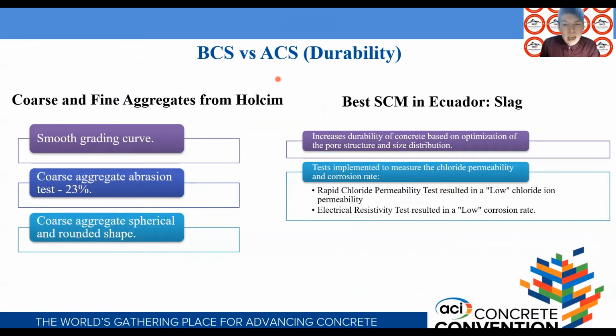In durability and performance, the particle size distribution of the mixture resulted in a smooth grading curve that meets allowed limits based on the characterization of coarse and fine aggregates from Holcim. But the coarse aggregate is the common variable that gives durability principally to the base case and reciprocally to the alternative case, due to its 23% mass loss in abrasion test along with its spherical and rounded shape.